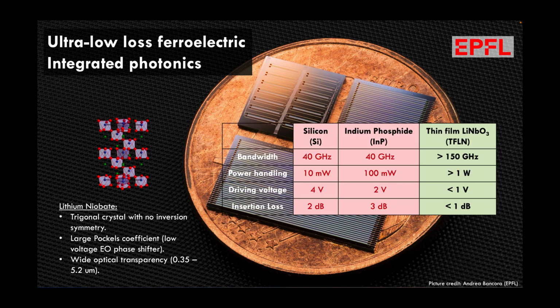And so first of all, what is interesting about lithium niobate and also lithium tantalate? These are materials that have, as I said, a large Pockels coefficient. And so what this allows them to be used for is modulators. And the modulators based on silicon and indium phosphide typically have a limited bandwidth of about 40 gigahertz. With thin film lithium niobate or lithium tantalate, you can have bandwidth that theoretically even extends to 300 gigahertz, so